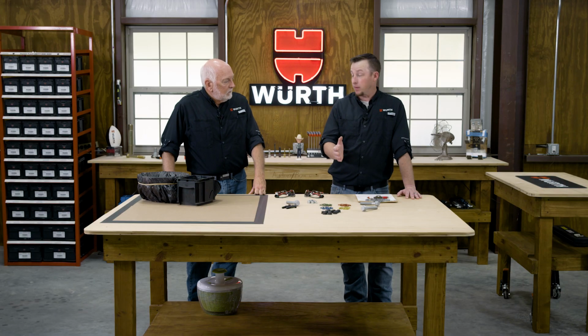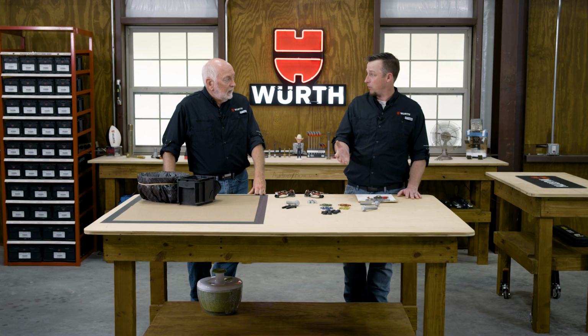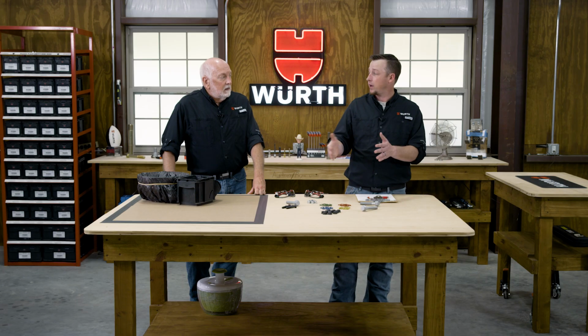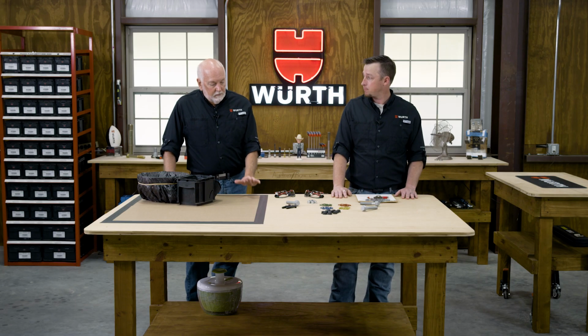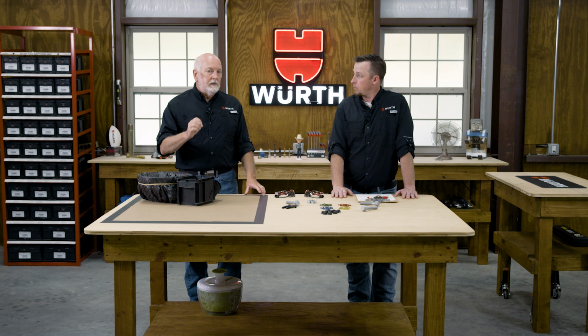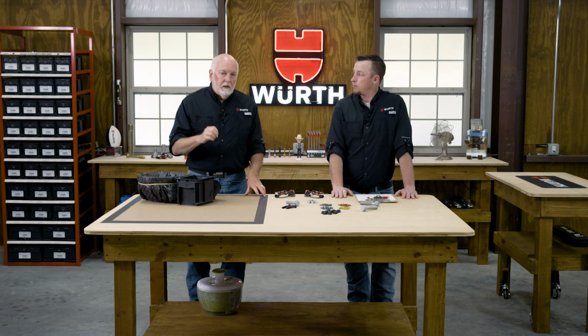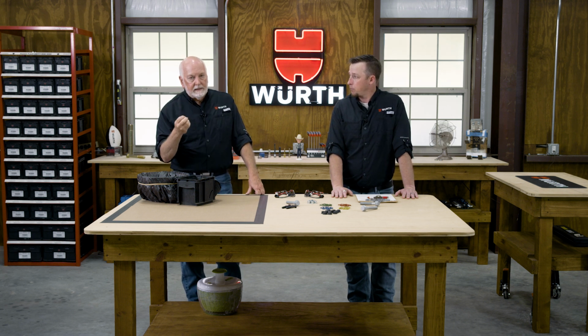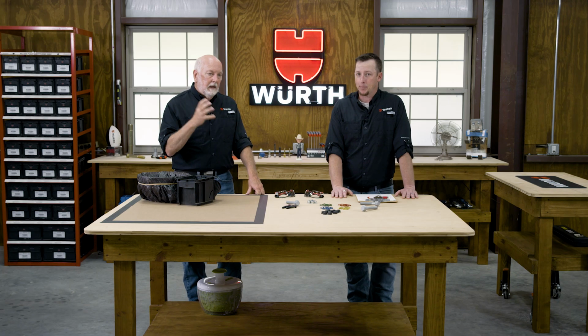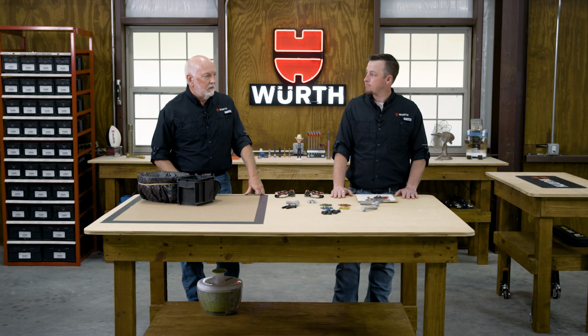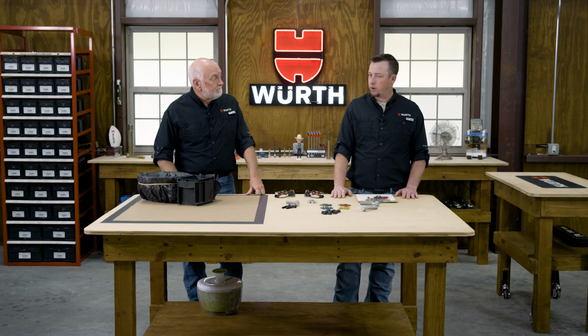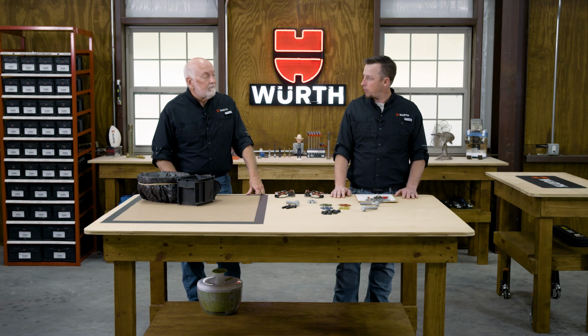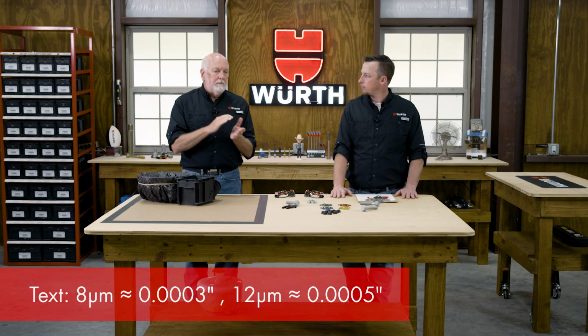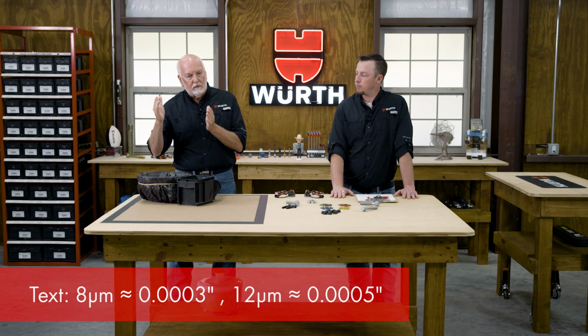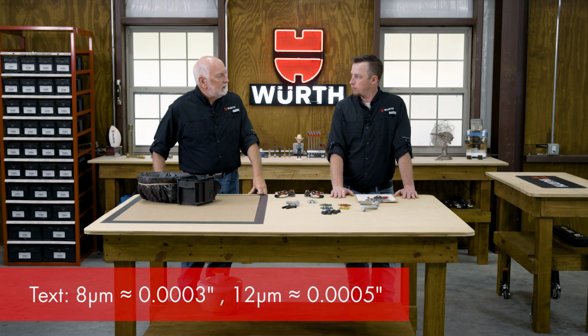And actually, I think the biggest benefit is it's affordable. So it's something we can look at as a replacement to zinc plating. In terms of affordability, the thin coatings down at the 240 hour range are price competitive in large bulk with electroplating in the high range of electroplating corrosion resistance. So we're seeing a lot of customers making a switch here. Right. So the thickness starts at about 12 microns, is that about right? Yeah, anywhere about 8 microns for the real thin coatings, upwards to about 12 to 14 microns for the thicker coatings and the higher corrosion resistance.